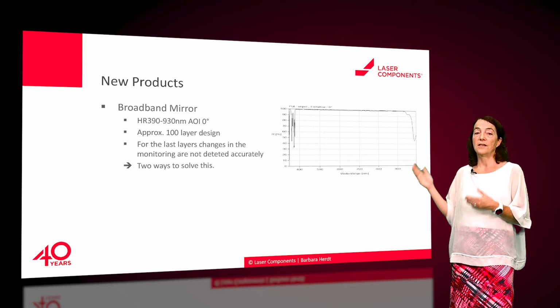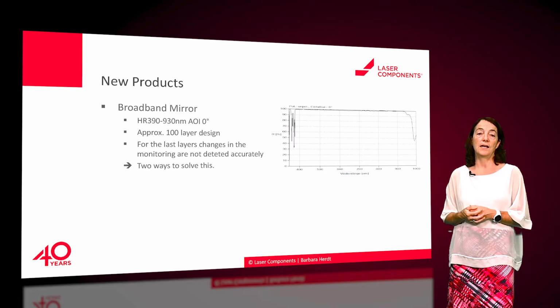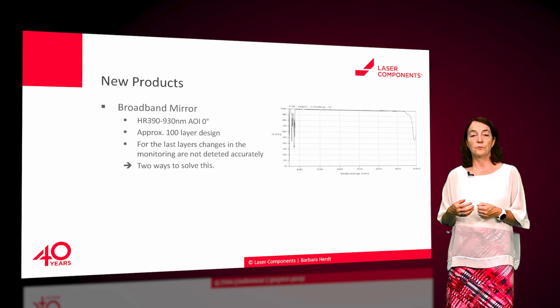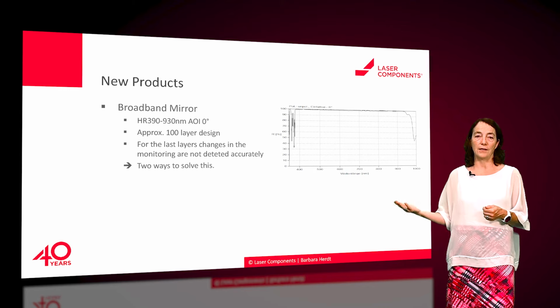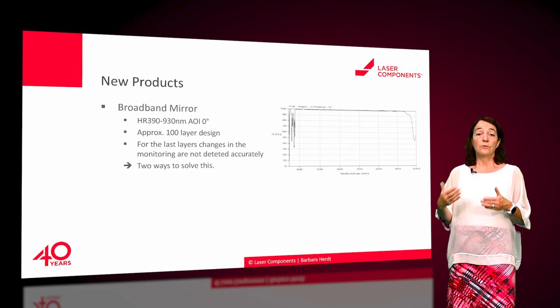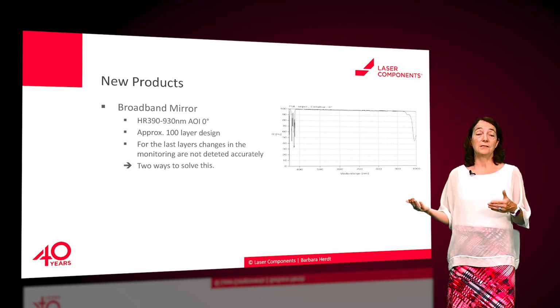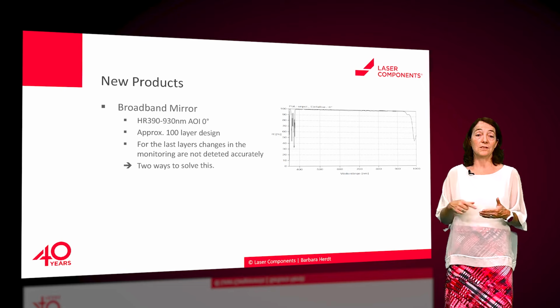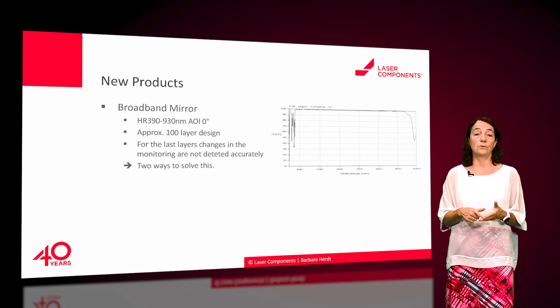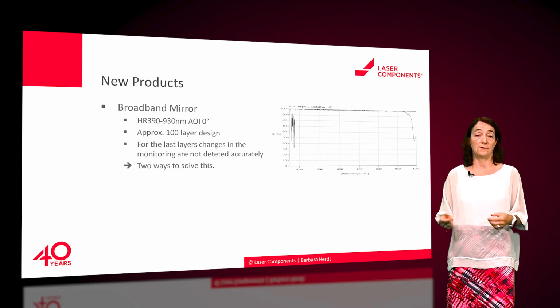We have here the example of a broadband mirror with high reflectivity from 390 to 930 nanometer at normal angle of incidence. To reach the specified reflectivity, a design with more than 100 layers is needed. For the last layers, the change in the transmission is very small and the accuracy would not be good enough to do a good coating, fulfilling all the specifications.